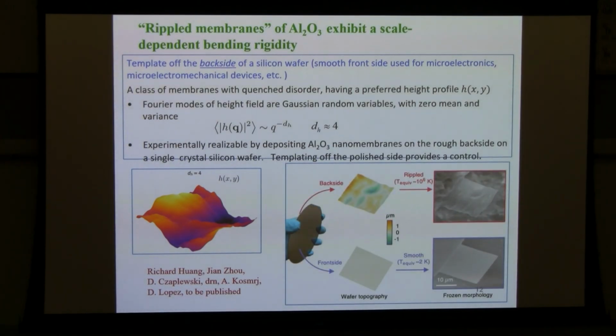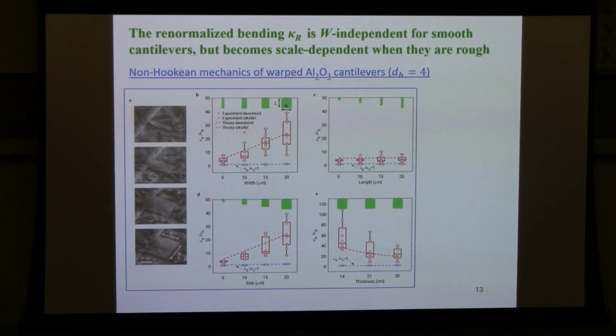And what these guys were able to do, using that silicon wafer, and Aaron said the $20 is too much. Now it's probably a huge markup. So this is the front side that everybody uses to make devices. They made a little aluminum oxide diving board from the top side. On the back side that most people don't use, they made one of these rippled things, a rippled analog with the same dimensions. And then they could vary systematically the length and the width, and see really what's happening with these elastic constants. Are they scale dependent? There's an analogous theory for this quenched problem that you can look at.